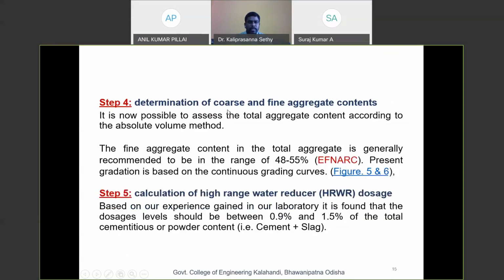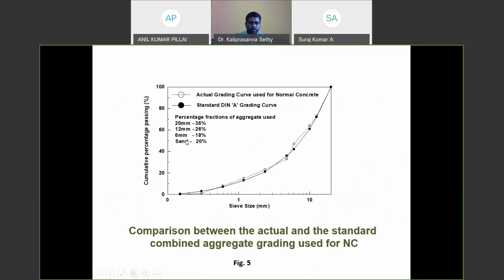And in step 4, we determined the coarse and fine aggregate content. It is now possible to assess the total aggregate content according to the absolute volume method. Like in conventional concrete, the fine aggregate content in the total aggregate is generally recommended to be in the range of 48 to 55%, as shown in the table provided by EFNARC. And the present gradation is based on the continuous grading curves. From these grading curves, you can see the gradation of the size of aggregates we have used for the development of normal and self-compacting concrete.